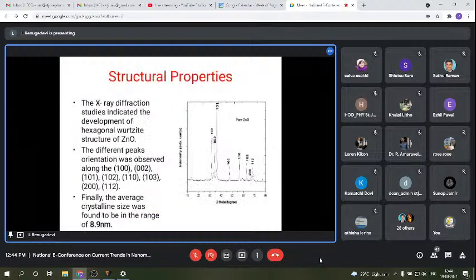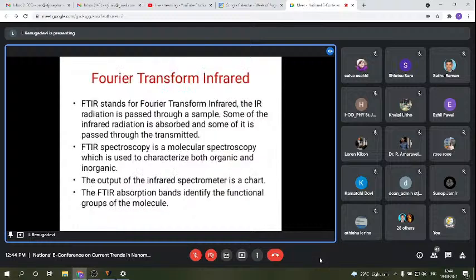In our method, the XRD graph was plotted from the X-ray diffraction studies. The structure was found to be the hexagonal wurtzite structure of pure ZnO. Different peaks were observed along the HKL values. These are the HKL values of this XRD. Finally, the average crystallite size was found to be 8.9 nanometers in our XRD result.